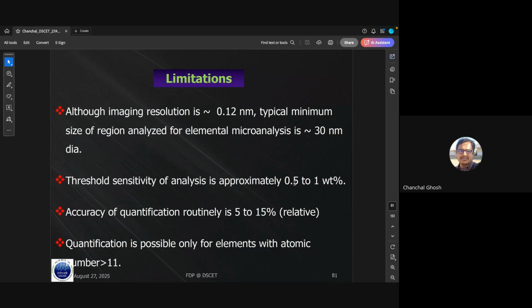Sensitivity is something around 0.5 to 1%. Below that you cannot get it. If it is above, definitely you can go for the EDS. But if your element is present below 0.5%, you cannot go from that part. Quantification is 5 to 15%. Roughly that is the accuracy it can give you.